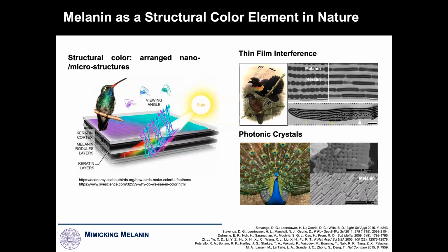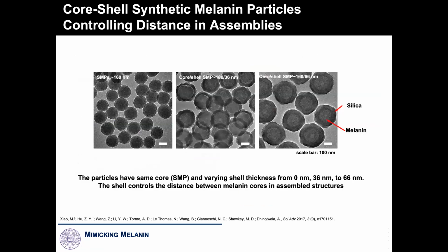Our attempt at this was to make core shell particles. So what we did was make melanin particles where the core is 160 nanometers in size. And then we grew silica on the surface. So this is our high refractive index core, low refractive index shell. And then we assemble them into films and three-dimensional objects. So what we're doing is holding the core constant and varying the shell so that the distance between the high refractive index material in the assembled objects is variable.